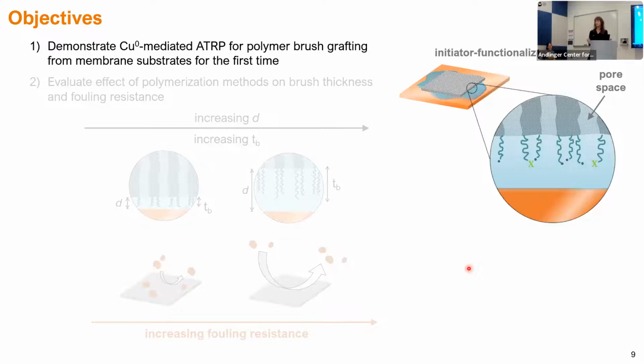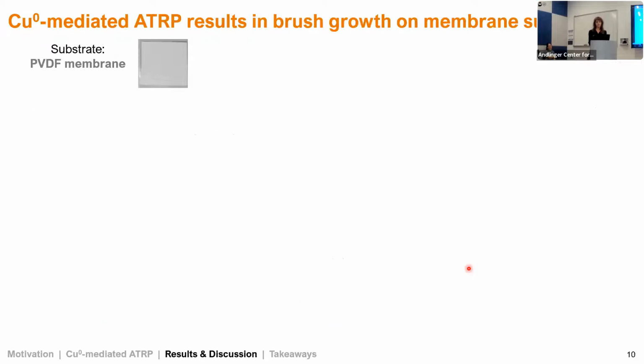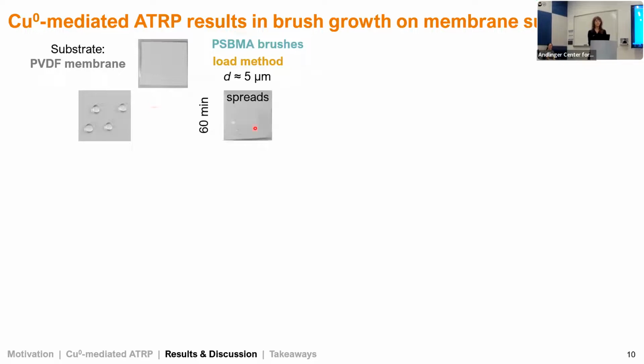Okay, so towards our first objective, looking at modification of membranes using this method. Here we have our microfiltration PVDF membrane. This membrane is relatively hydrophobic. It has a contact angle of approximately 130 degrees before and after plasma treatment. So after modification with our brush layer, and I'm going to start here with the load method at our smallest distance D, after 1 hour of polymerization time, we see that water readily spreads across the surface, indicating the presence of these hydrophilic brushes.